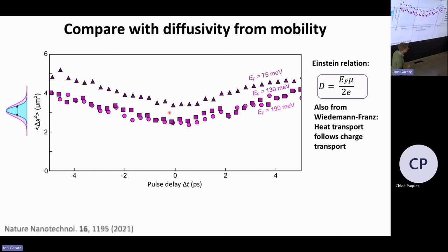Now the nice thing is, we can also measure electronic transport. So we can see if the diffusivity that we're getting makes any sense. And the way it makes sense is through the Einstein relation. The Einstein relation basically tells you how the mobility is connected with the diffusivity. And this is the case specifically where electronic charge is moving and electronic heat carried by charge is moving. So there are no phonons involved here. You can actually get the same equation when you solve the Wiedemann-Franz equation. So all the German-speaking or German-named famous scientists agree on this formula. So it would be really nice if it also agrees with our data.